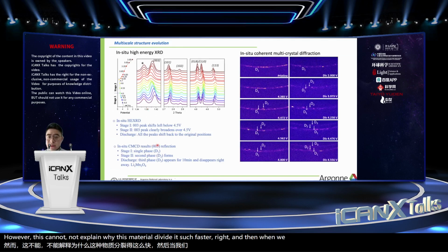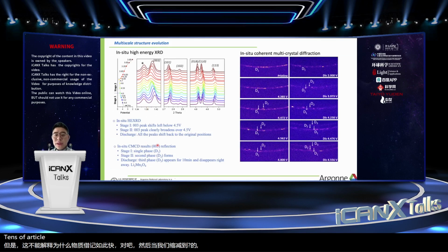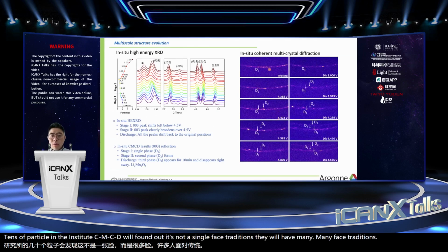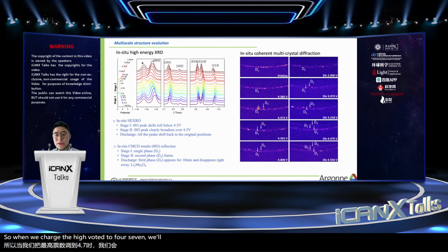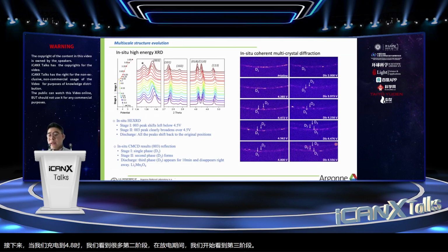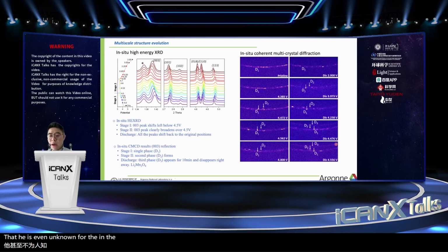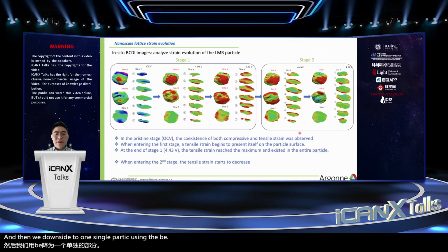And then when we downsize to the tens of particles using in situ CDI, we have found out it's not a single phase transition. They will have many phase transitions. So when we charge to high voltage, 4.47, we will start to see the second phase, and this phase actually is irreversible. And then when we charge to 4.8, we see a lot of the second phase. During the discharge, we start to see a third phase that is even unknown in the battery community. So clearly, the CDI told us it is irreversible. And then we downsize to one single particle using BCDI. We can tell you why this material has the irreversible phase transitions.